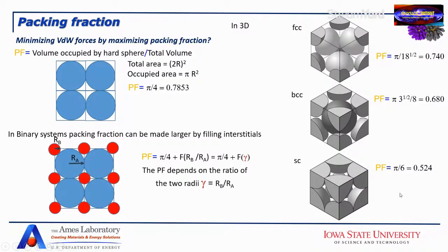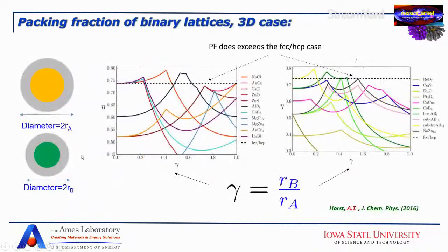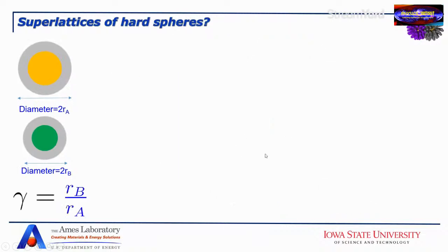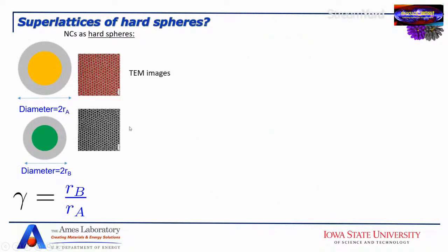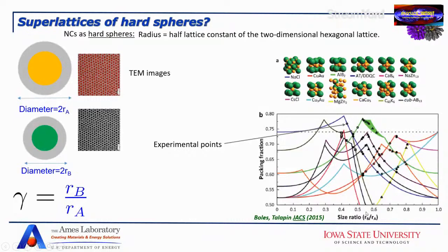So now when you go to 3 dimensions, instead of getting just one packing fraction, what we get is a function that depends on the ratio between the two spheres. And this is what it looks like. Those are different lattices, and you see that these different lattices typically have a maximum of the packing fraction that happens for different values of gamma, the ratio of these two numbers. When we do an experiment, we can assign a radius to this, and then we can plot it, and what you see here is that the experiments typically happen around the maximum of the packing fraction.